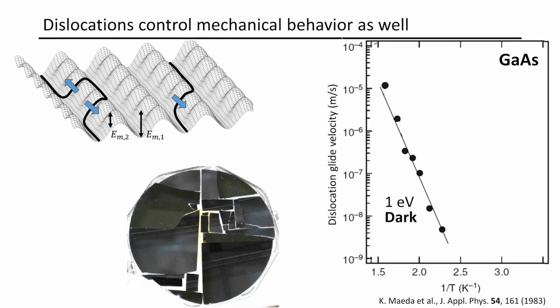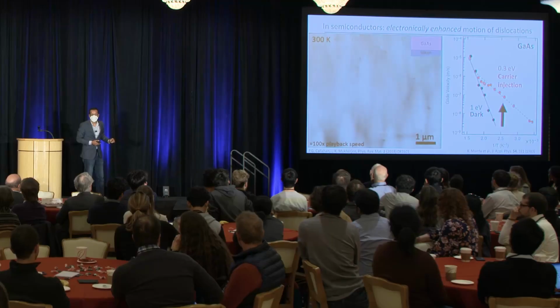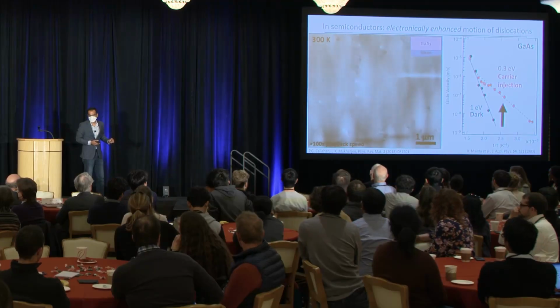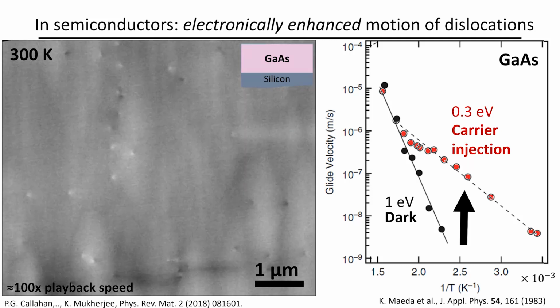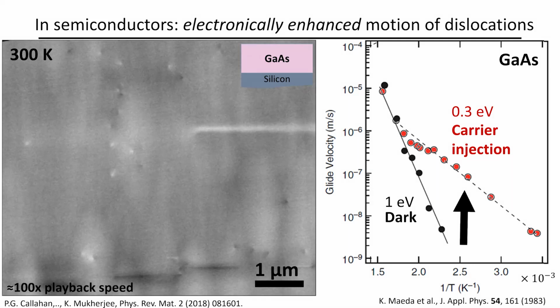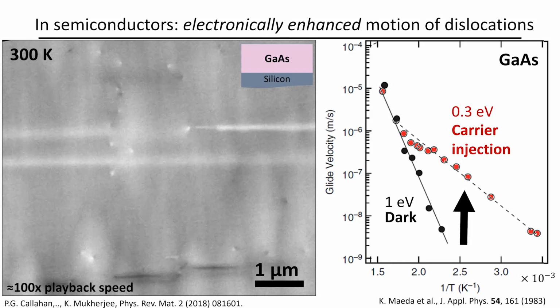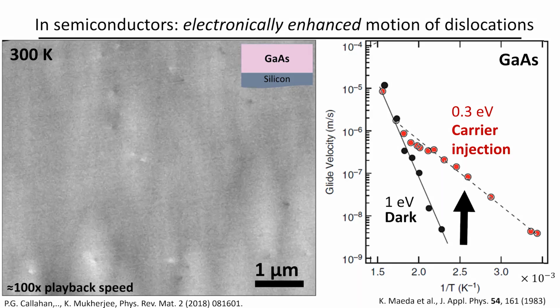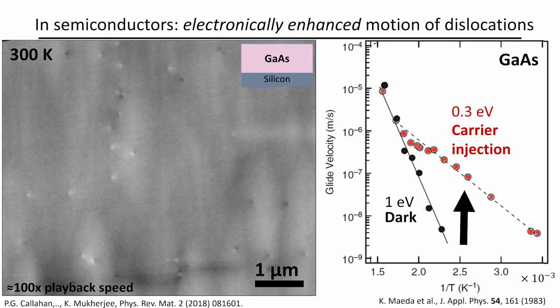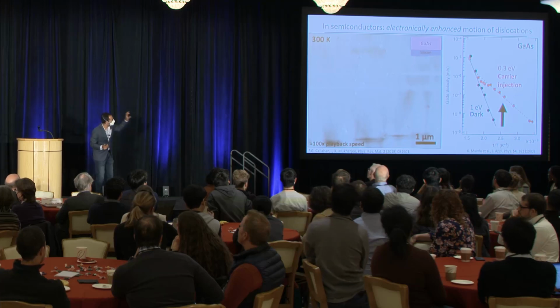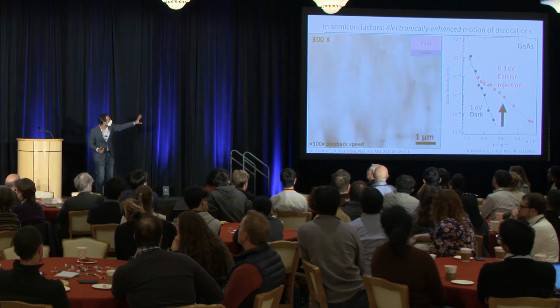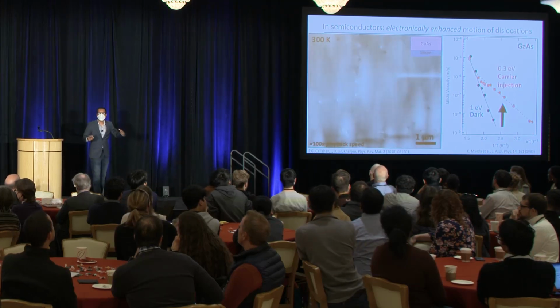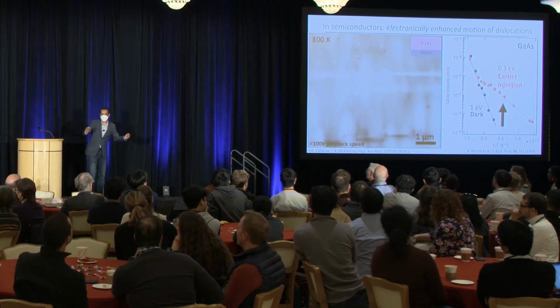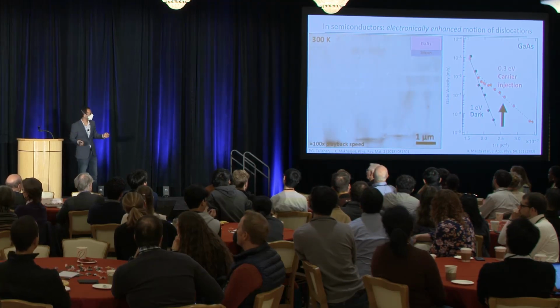Normally, dislocations in the dark have very high activation energies. But when you inject electrons in them, they actually start moving at room temperature. This is one of the most interesting phenomena that exists in semiconductors. It's a coupling of electronic properties and mechanical properties. So you can see just by injecting carriers into the semiconductors at room temperature, we're converting an otherwise brittle material into something soft, into something plastic, right?